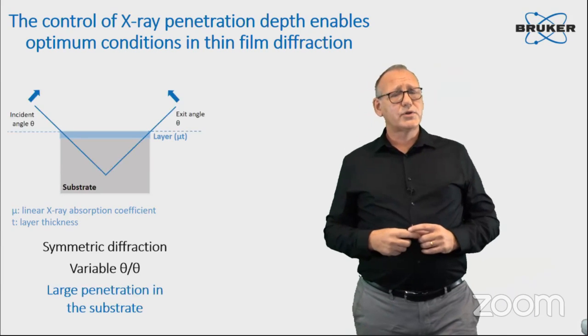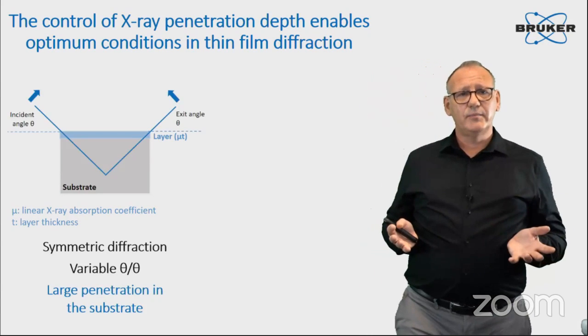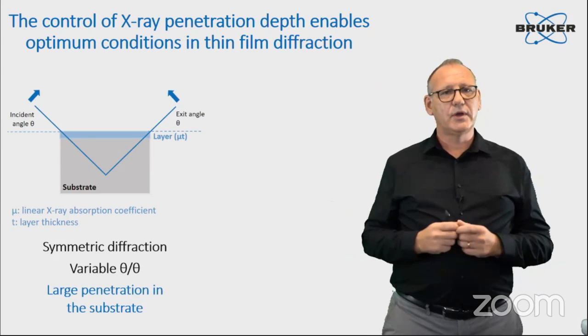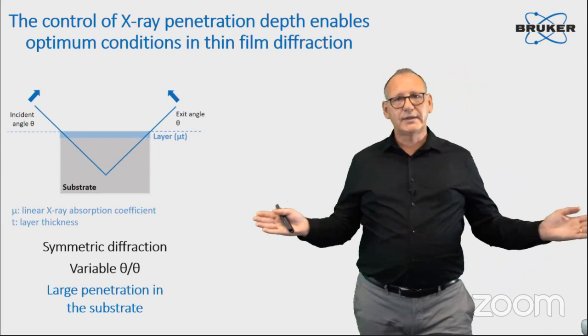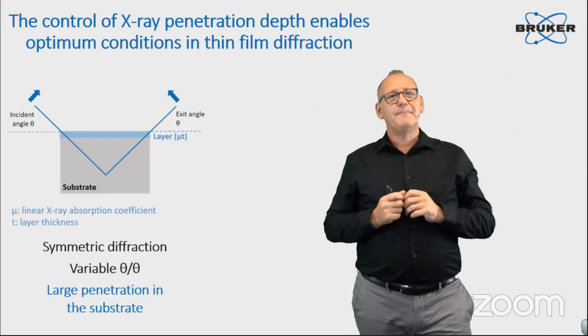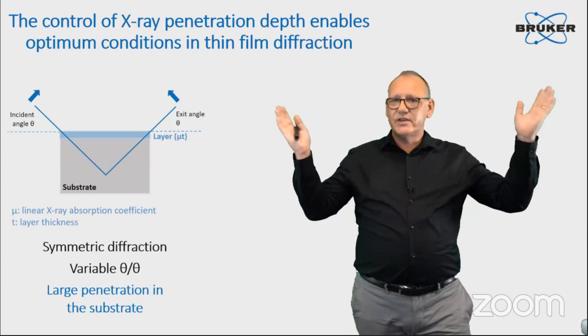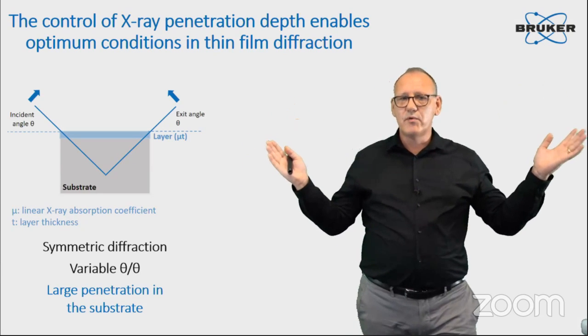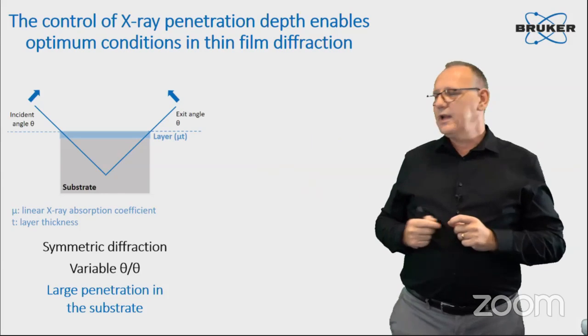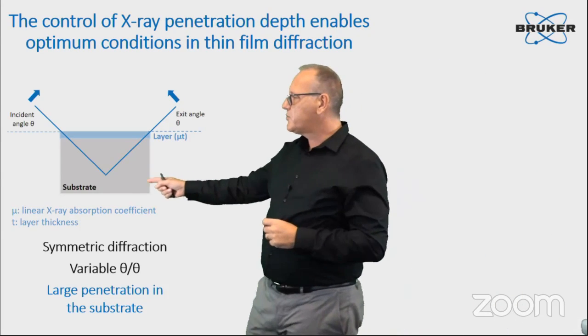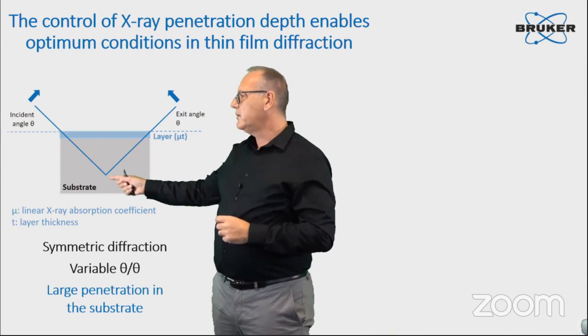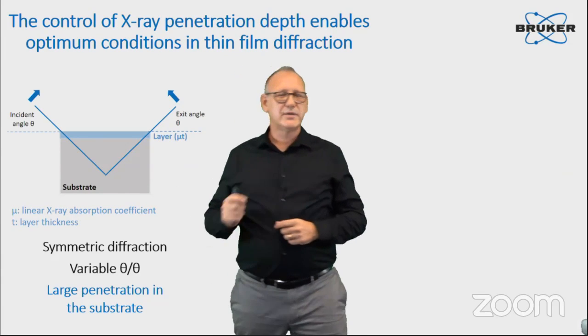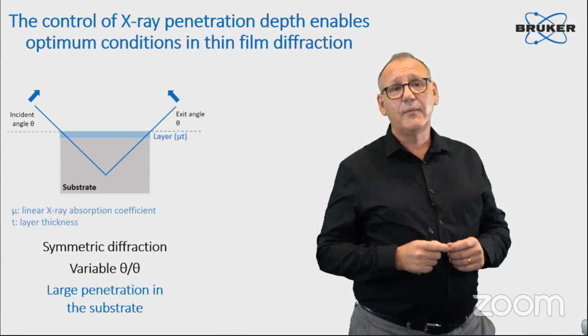If you try to measure this sample with a standard diffractometer, a powder diffractometer you may have in your lab with a theta-theta goniometer, this is a symmetric diffraction, so tube and detector move simultaneously. You will have, as you see here, a very large penetration depth into the material. And probably the substrate signal will dominate the overall diffraction pattern.